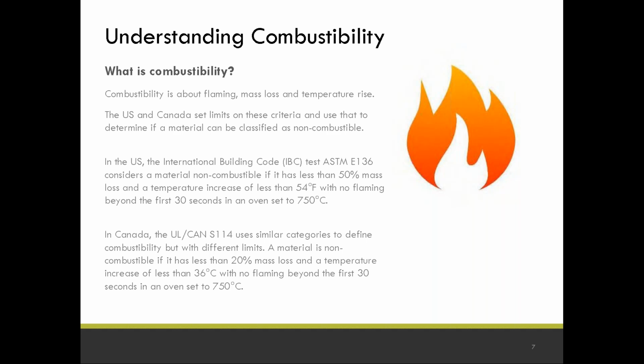In the US, the IBC code test for combustibility is ASTM E136, and it considers a material non-combustible if it has less than a 50% mass loss, a temperature increase of less than 54 degrees Fahrenheit, with no flaming beyond the first 30 seconds. And this is all set in an oven that is set to a 750 degrees C temperature. So those three things will determine whether or not a material is considered combustible in the US.